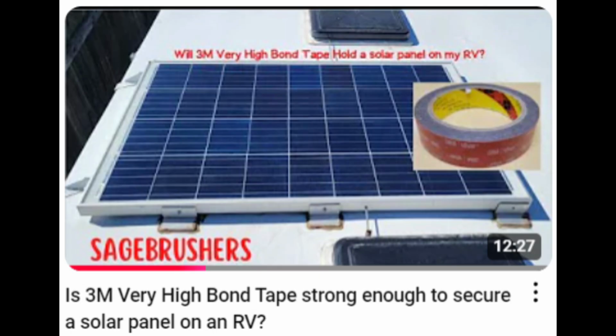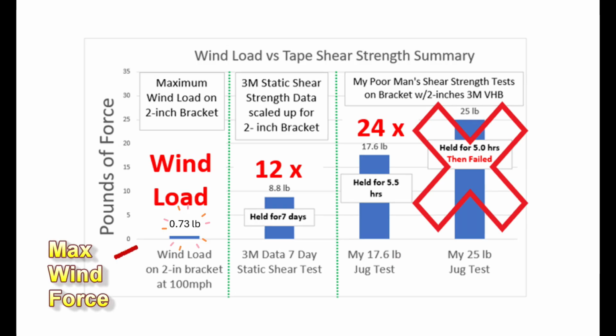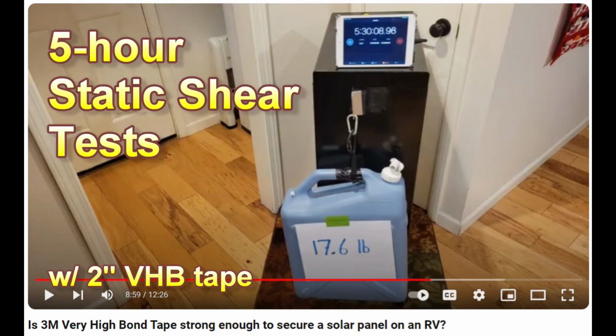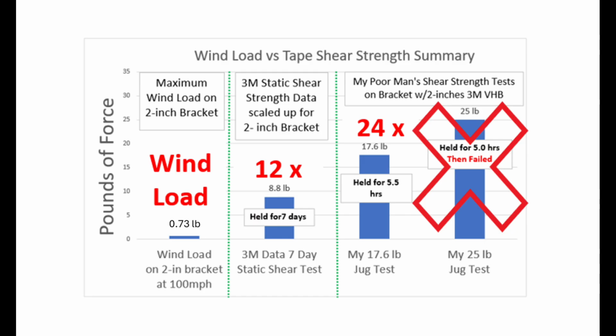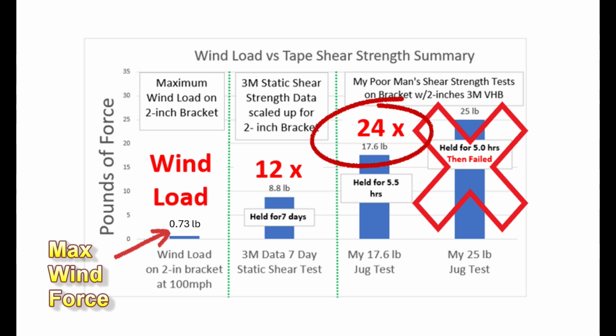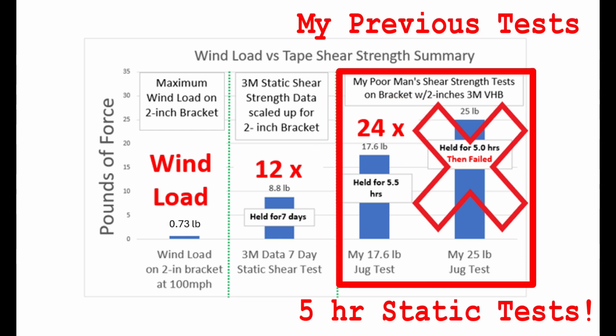In my original video on the strength of VHB tape for no-drill solar panel installs, I estimated the maximum shear force due to winds, then measured the 5-hour static shear strength of 3M's 5952 very high bond tape. I demonstrated that the 6 2-inch brackets holding my panel would be 24 times stronger than the worst case force of 100-mile-per-hour wind. These tests are the same as my earlier static shear tests, which lasted for about 5 hours.